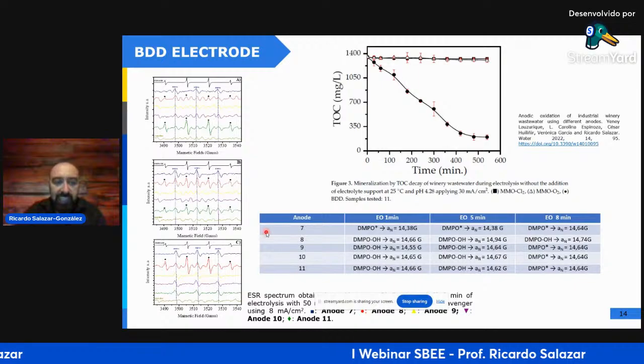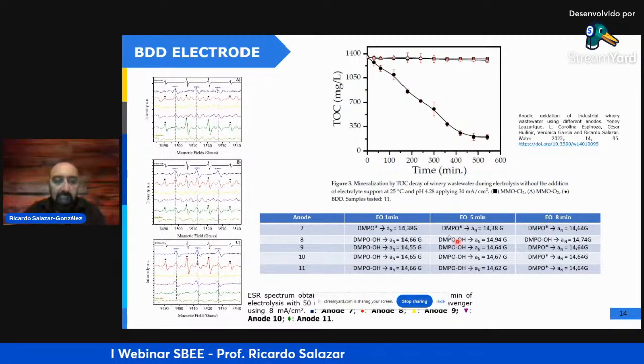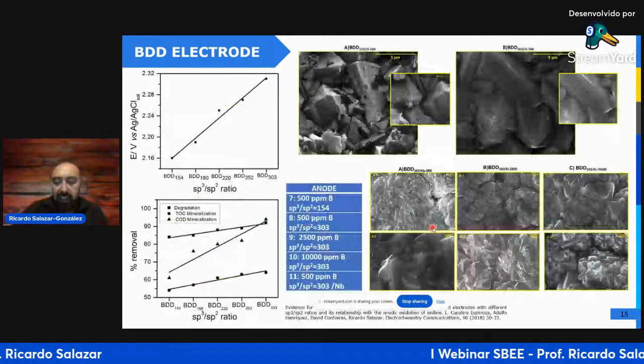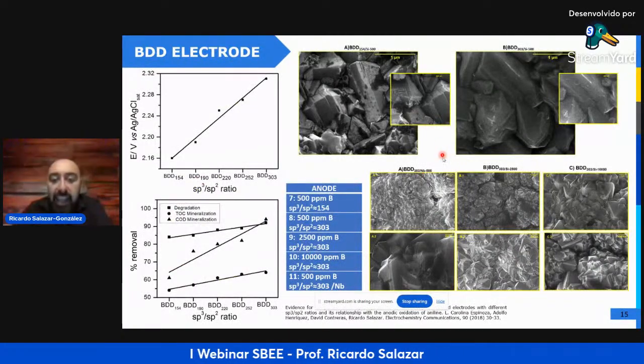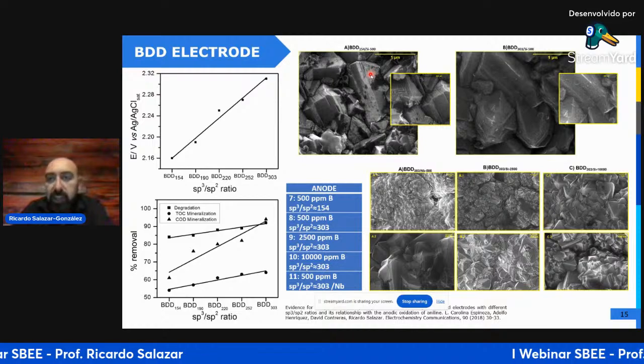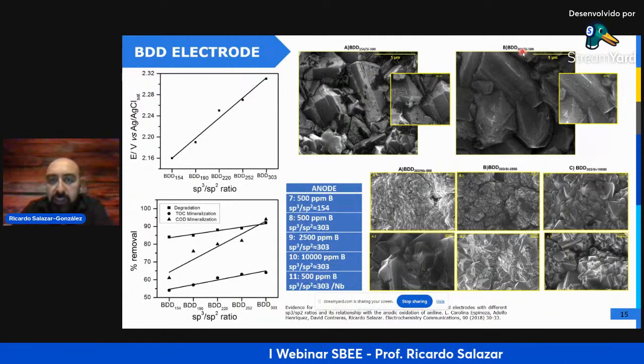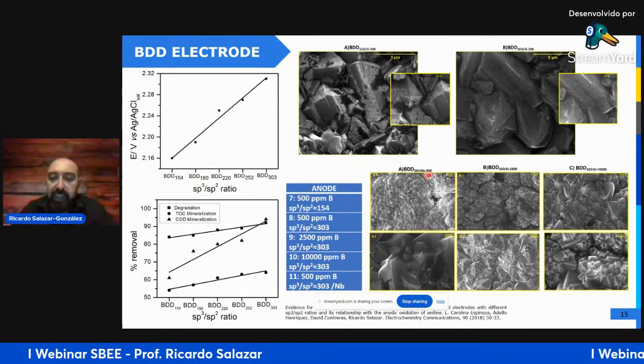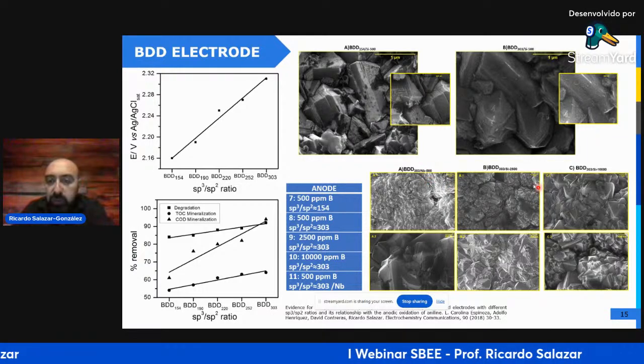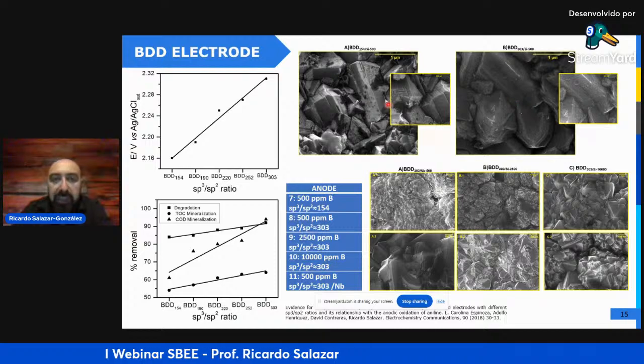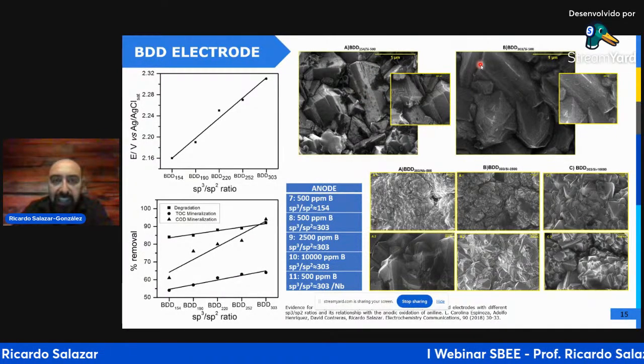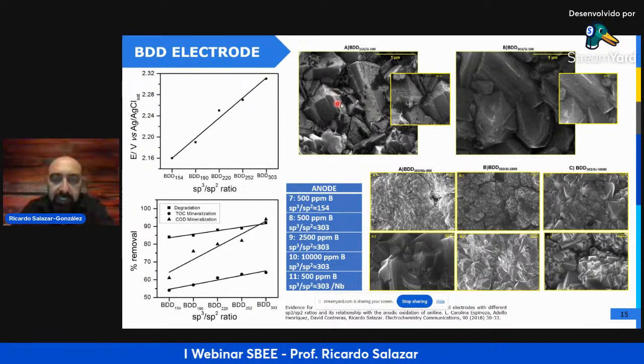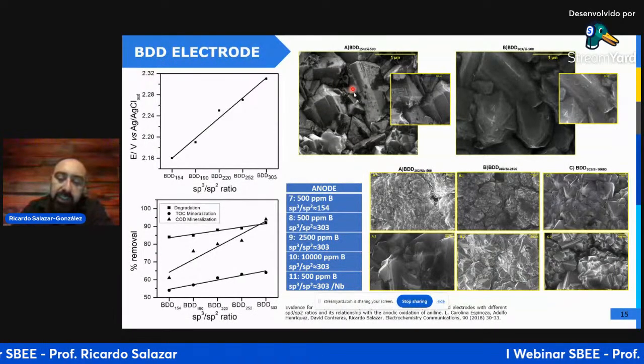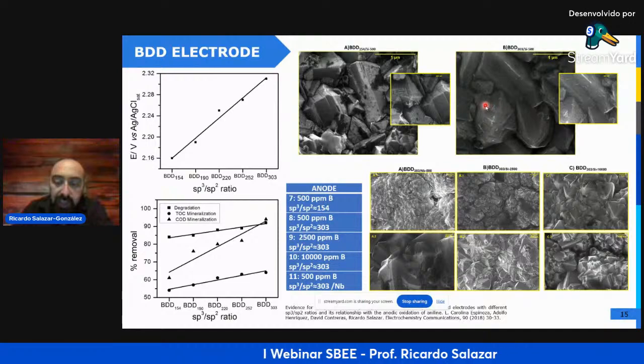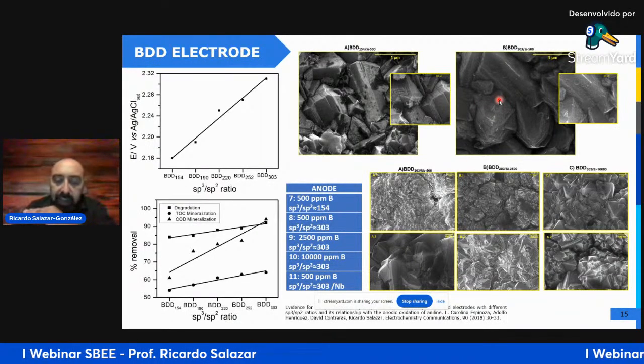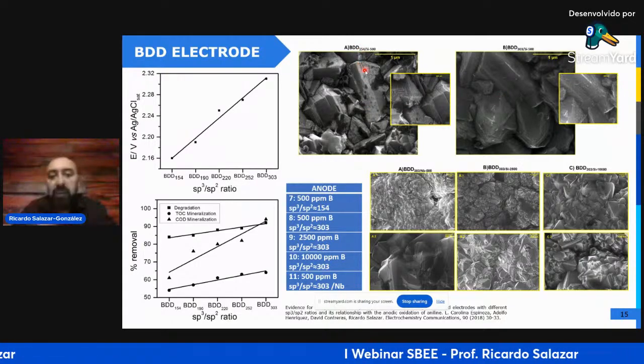And we can determine the concentration of the hydroxyl radicals by EPR experiments. With respect to the surface of the electrode, for example, we have different kinds of BDD electrodes with different proportions of graphite and diamond on the surface, with different substrates, silicon and niobium, and with different concentrations of boron on the surface. In the case of BDD with different ratios of diamond, this one has more diamond than this electrode, and it presents a high roughness on its surface, which is of the polycrystalline type. And this roughness depends on the diamond and graphite ratio.